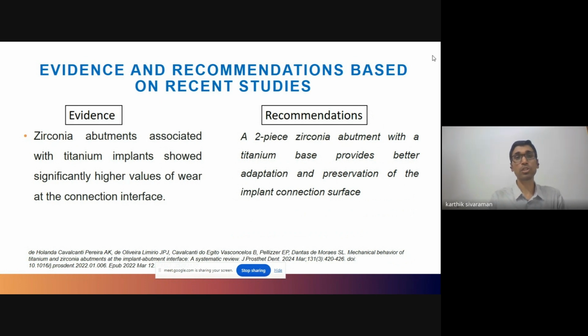We know that there is a difference in modulus of elasticity between these two materials. So we have titanium with a lower modulus of elasticity and zirconia with a higher modulus of elasticity. So even though the titanium can undergo an elastic deformation, the zirconia will resist it, and there might be a greater wear at the interface between these two materials. It will not be similar to how a titanium abutment will be placed on a titanium implant. The other finding in this study was that this wear will vary depending on the geometry of the connection. If you have an internal connection implant, the wear will be more because the external connection will ensure a greater surface area over which the stress will be distributed.